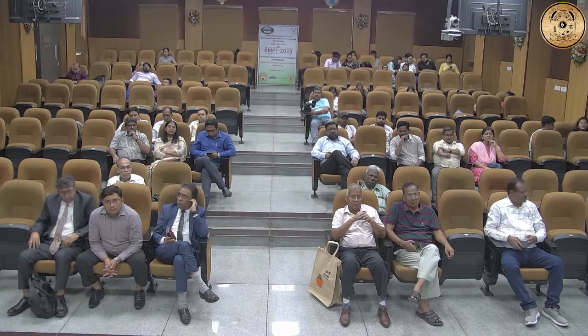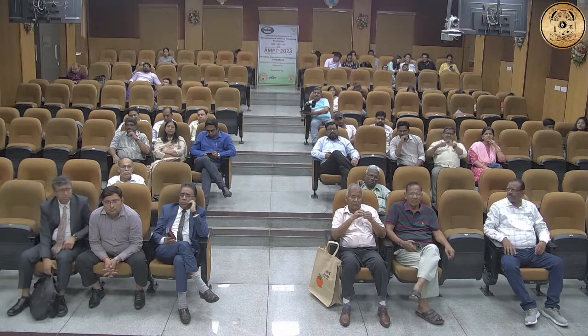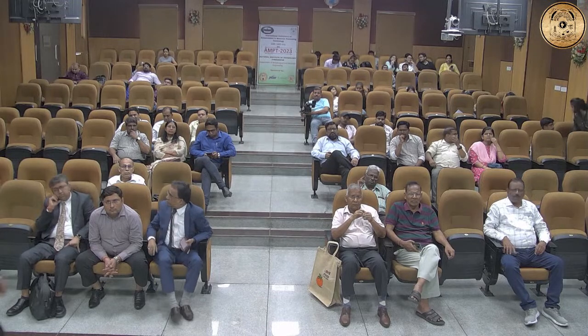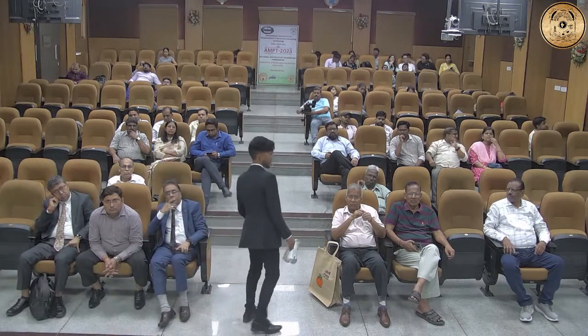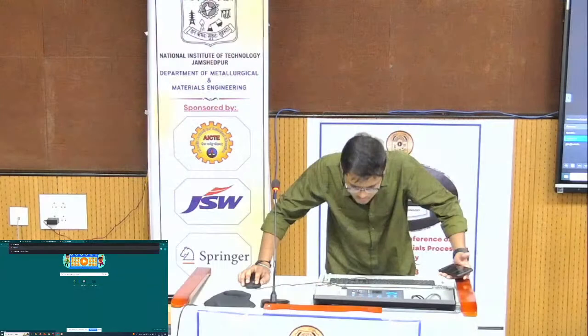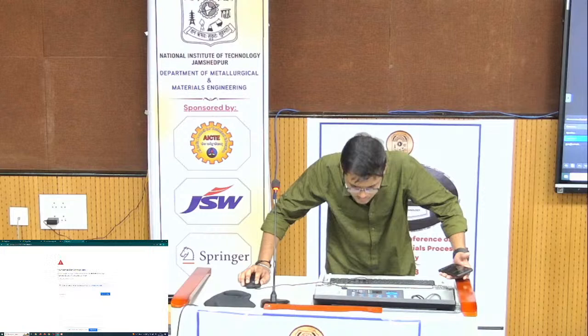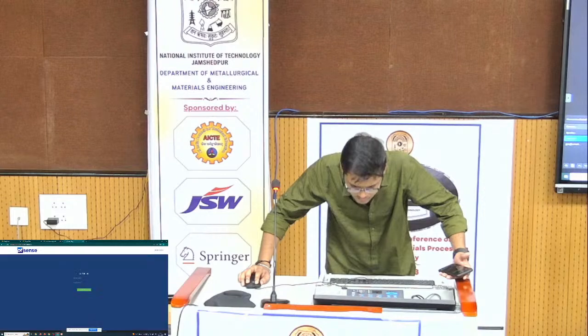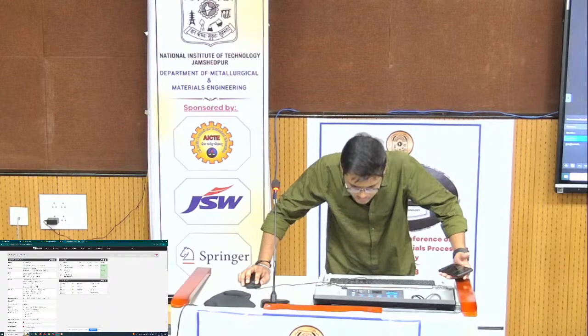So the signal amplitude, etc., of the Barkhausen, they have to be kept in view. I will not go into details. Magnetically induced velocity changes. I will spend 2 minutes on the X-ray diffraction techniques. A, I like it. B, this is perhaps the most important technique for measuring the surface residual stress, which in turn controls the fatigue properties of the components, which are all rotating components, be it aircraft components, automobile components, all of them which rotate. Fatigue is important.